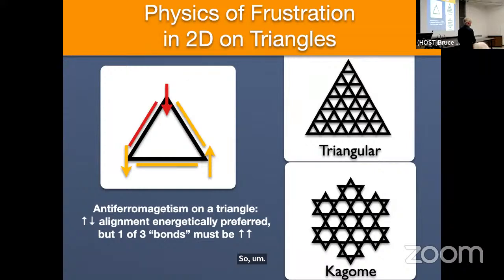Triangular architectures are very common in nature. You can have a 2-dimensional net made by tiling 2 dimensions with edge-sharing triangles, and that forms the triangular lattice, very common in nature. It's the basal plane of all hexagonal crystals. Something less common in nature, but still not uncommon, is a network of corner-sharing triangles, referred to as the Kagome lattice. Both of these are networks of interconnected triangles, and if we decorate a single triangle with classical magnetic dipoles that are antiferromagnetically coupled, we would minimize the energy by forming antiferromagnetic correlations on each side of the triangle.